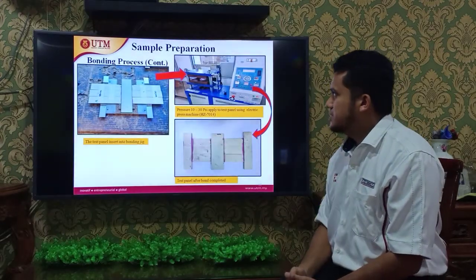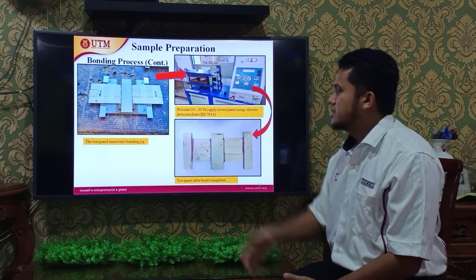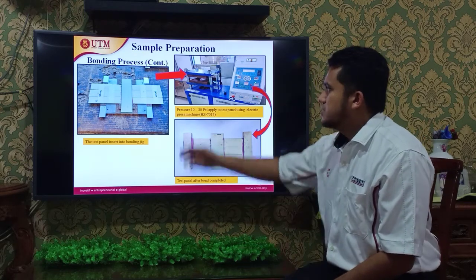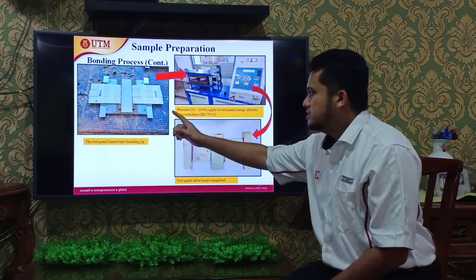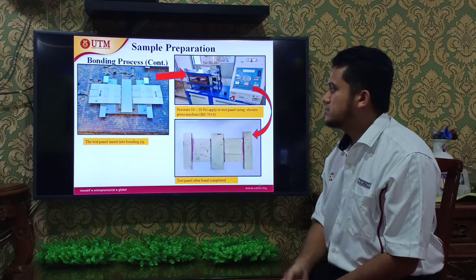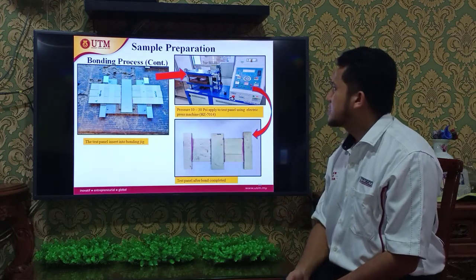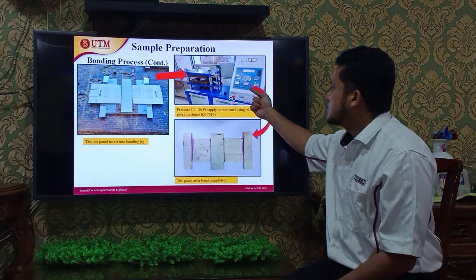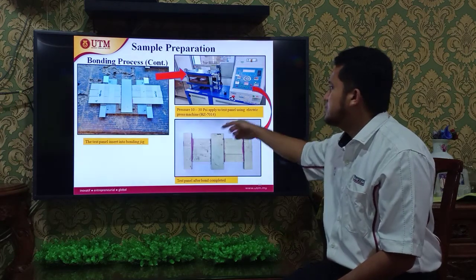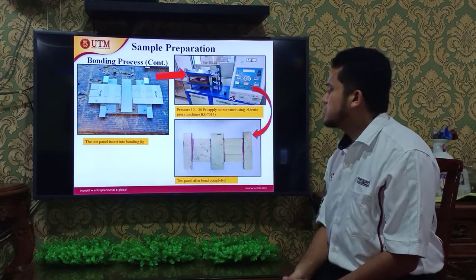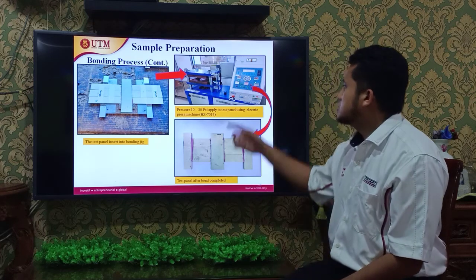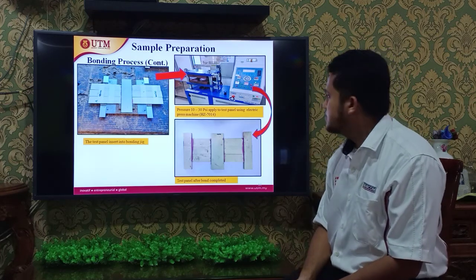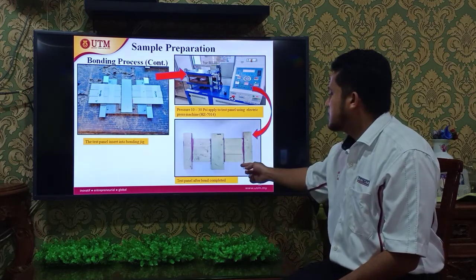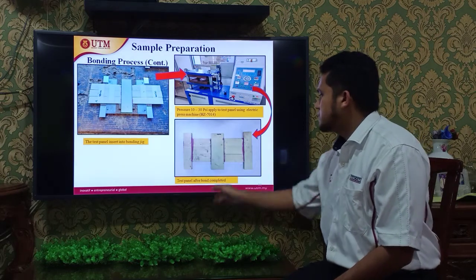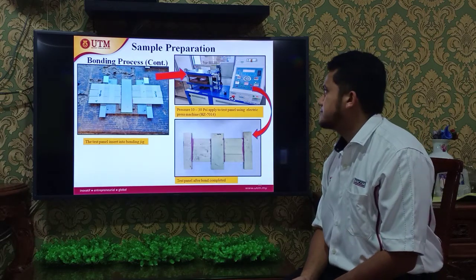As we see, this is the bonding process. The picture shows the test panel inserted into the bonding jig. This is the press machine, pressure 10 to 30 psi, applied to the test panel using an electric press machine. And these pictures show the test panel after bonding is completed.